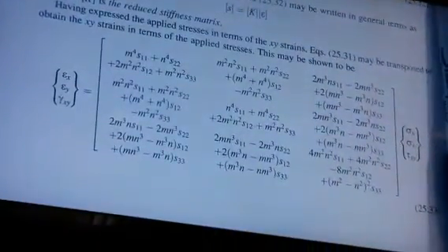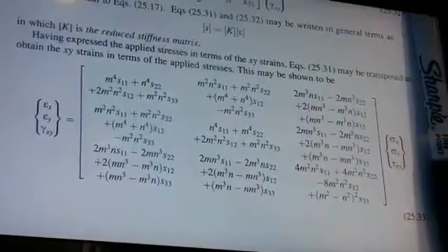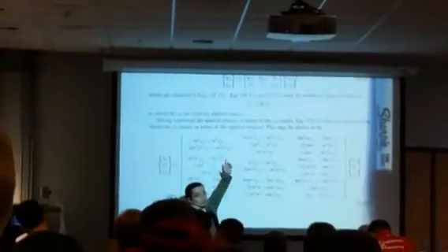And inversely, is this one. In that equation, you have the stress on the left, strain on the right. You can do the inverse of that matrix. You get strain on the left, stress on the right. You get another 3x3 matrix. So this matrix is called the compliance matrix. That matrix is called the stiffness matrix. And that one is K. You see, there's a K. Yes, there's a K there. That one is for the stiffness matrix.